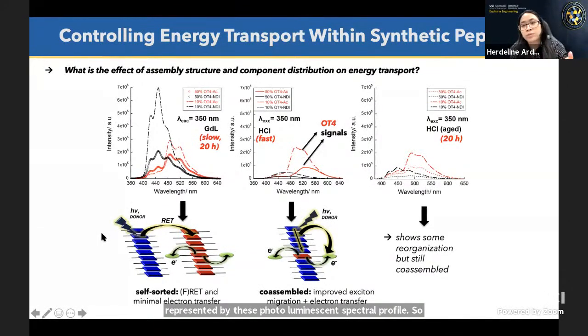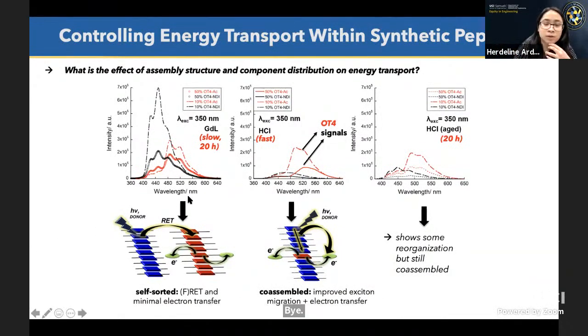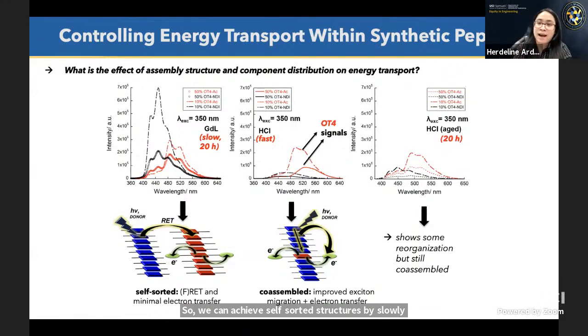So we control the rate of the assembly by varying the trigger that we used. So we can achieve self-sorted structures by slowly assembling them over 20 hours. And then we have one that is more fast and leads to the co-assembly of the different chromophores that we have. And what's interesting is that even if we age these co-assembled systems, they still do not reorganize into the self-sorted systems, meaning that through variations in the trigger method, we can control the structure. And by controlling the structure, we could then control the energy transfer processes that are happening in these